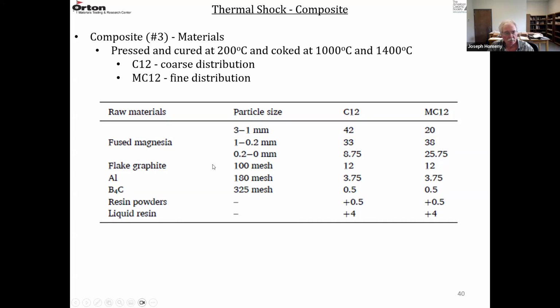So the graphite content was 12% constant. The antioxidation agents were constant, 3.75 for aluminum metal and 0.5 for boron carbide. But you can see this was 42% coarse, and this is down to 20. The medium size was 33. This is up to 38. And the fines here were about 8, and now they're 25. So C12 is much coarser than MC12.